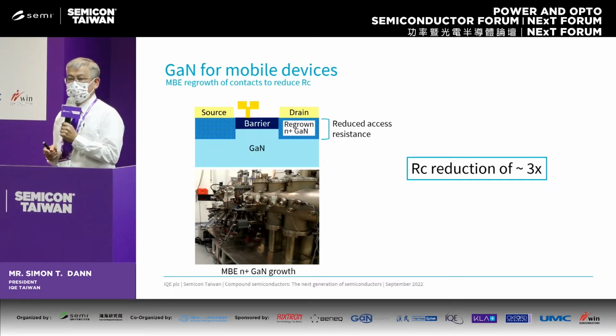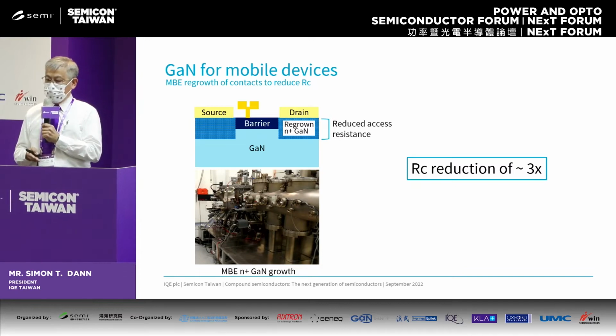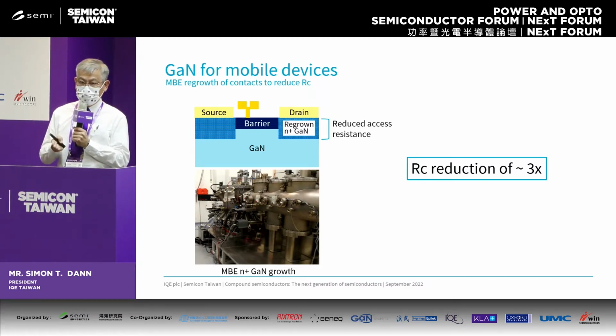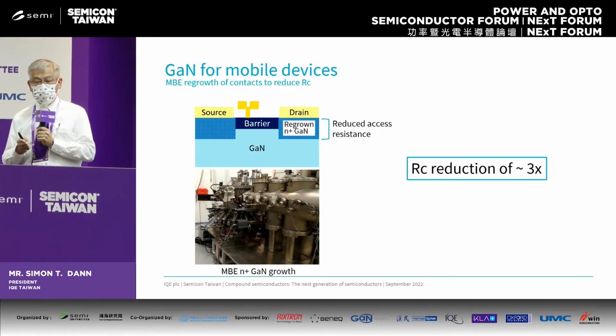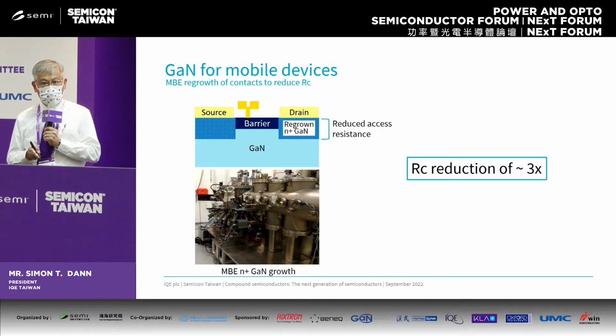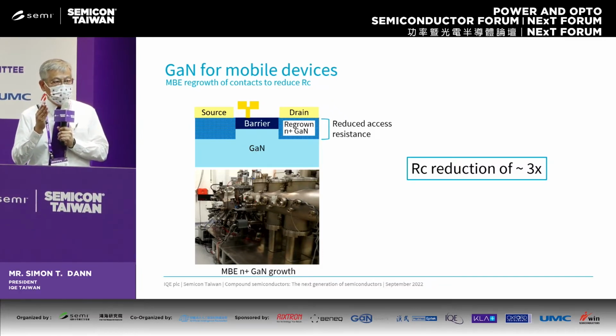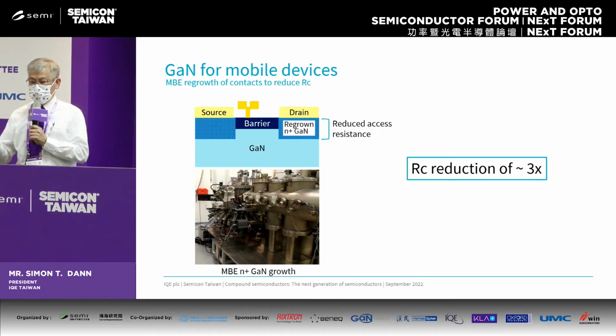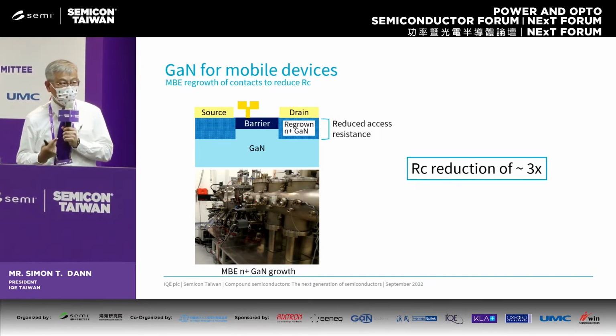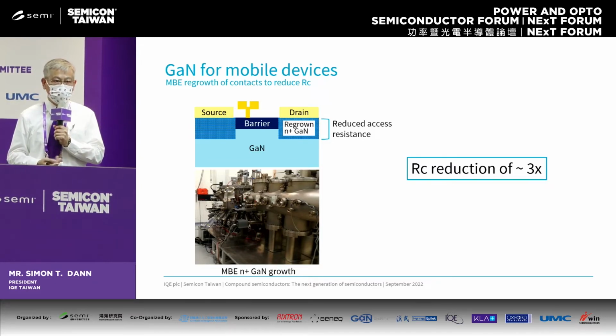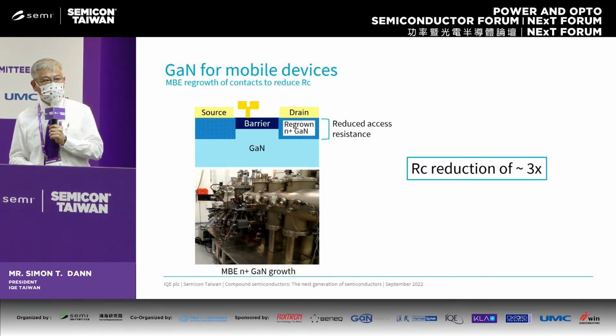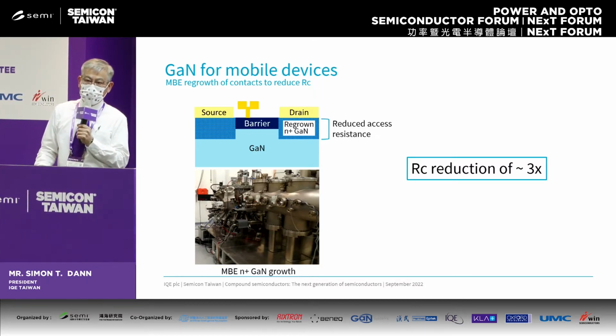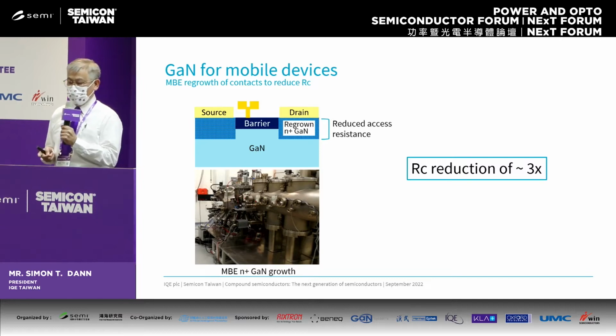And this actual one is available for the gallium nitride for mobile device, which shows we have a capability to overgrow the N+ gallium nitride by MBE system to reduce the contact resistance 1/3. So the heat loss at the drain can be reduced a lot according to this overgrowth technology. IQE is the only one in the world that providing both MOCVD and MBE technology to service our customers. And also Taiwan is the only site that equipped it with two technology at one site.